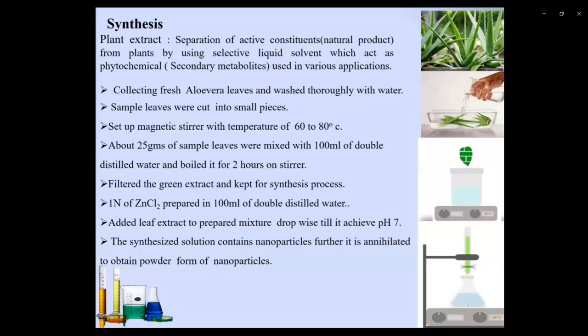On the other side, one normality of zinc chloride is prepared in 100 ml of double distilled water, and further leaf extract solution is added to the prepared mixture drop-wise till it achieves pH 7, which is supposed to obtain nanoparticles.